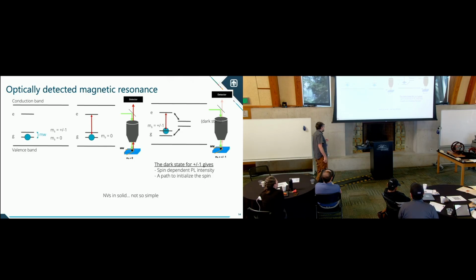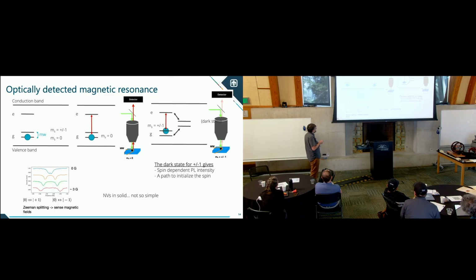Now, what that looks like magnetic resonance-wise is that here's a picture of the magnetic field. We're going to ignore a little bit of the details for a bit, but the 2.87 gigahertz is your optically detected magnetic resonance. This is the amount of photoluminescence as a function of microwave drive frequency. As you hit that resonance, you see a dip in the photoluminescence intensity.